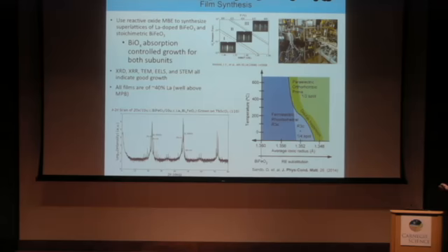This is well into the regime where we're not anywhere close to the morphotropic phase boundary. We used various characterization techniques: diffraction, reflectometry, X-rays, and various TEM. I'm going to show a bunch of TEM data. EELS and STEM all indicate good growth and high-quality films. As I said, this chemistry is important: all of our lanthanum-doped layers are well within the paraelectric state.